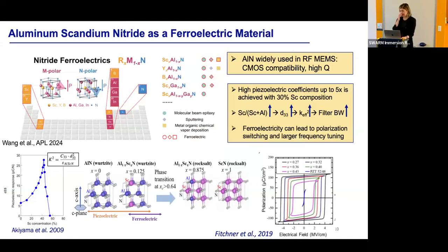So the first part is adding scandium to aluminum nitride, which is a widely used material for RF MEMS. It has been super popular because of the versatility in the deposition or growth. Sputtering aluminum nitride can be low temperature, so it can be deposited post CMOS, and usually gives you high Q. You can also use epitaxial aluminum nitride, which can be compatible with III-V semiconductor technologies, such as gallium nitride, all the III-nitride family electronics.